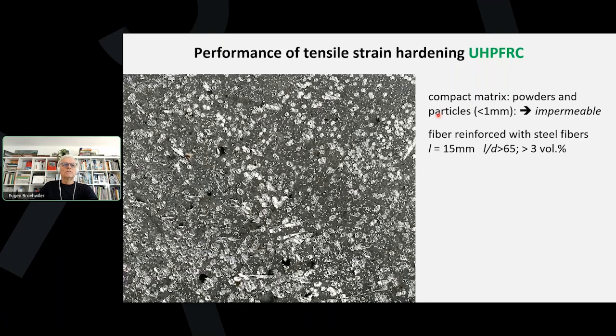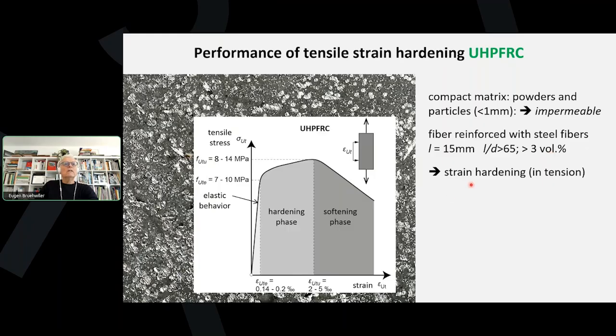As already mentioned, we have a very high amount, more than 3 volume% of steel fibers, short steel fibers in this material. 3 volume%, this corresponds to 250 kilograms per cubic meter of this material. That's a very high reinforcement content compared to reinforced concrete. Now, we need strain hardening behavior. When you see here on tensile stress strain diagram of UHPFRC, we can identify the elastic behavior, and then we have this so-called strain hardening behavior. And all of you will know this strain hardening behavior actually from steel. So the material UHPFRC behaves much more like steel under tension.